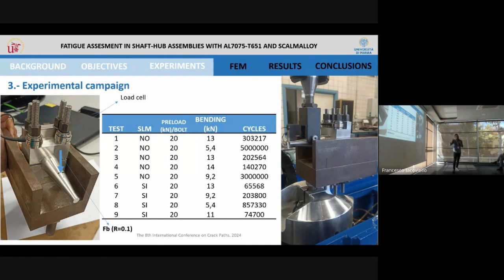Also, at the tip of the shaft, we apply a bending load with a load ratio of 0.1, thus ensuring that the hot spot will be at the upper part of the shaft. We did 9 tests, 5 with AL7075 and 4 with Scalmalloy, all of them with the same normal load. We varied the bending load between 5.4 kilonewtons and 14 kilonewtons in order to capture the whole range of life from 65,000 up to 5,000,000 cycles. These results will be compared later on with the predicted ones.